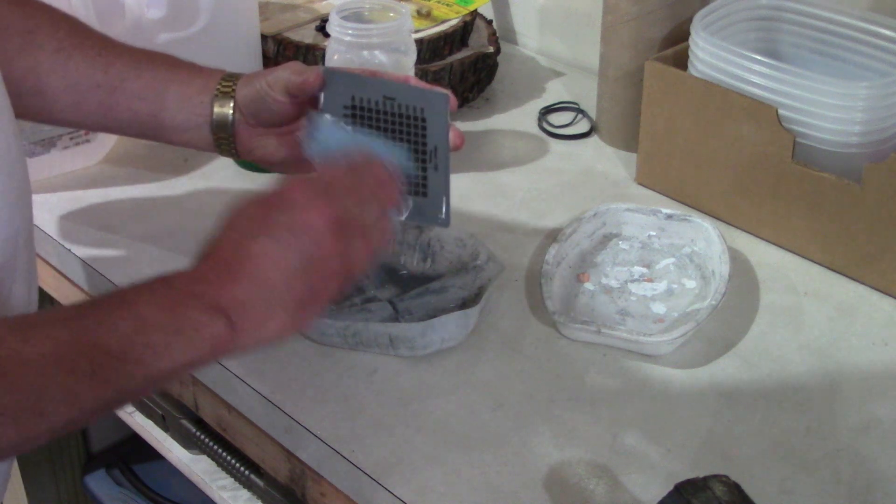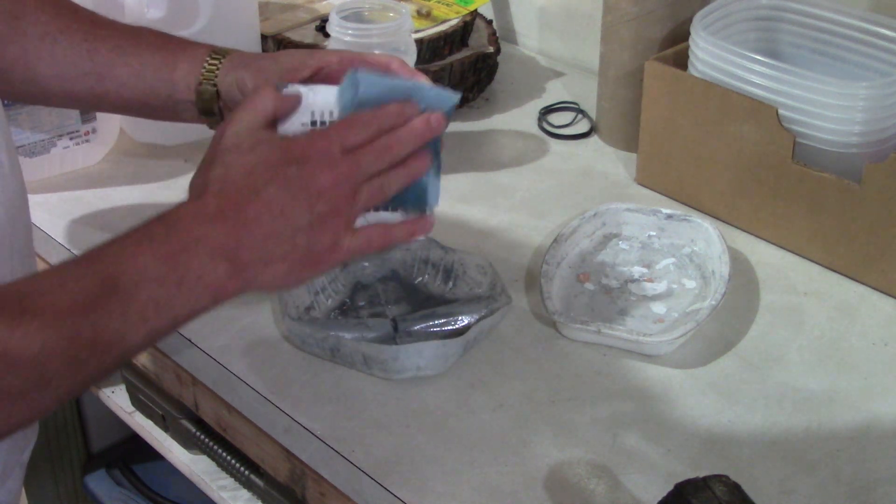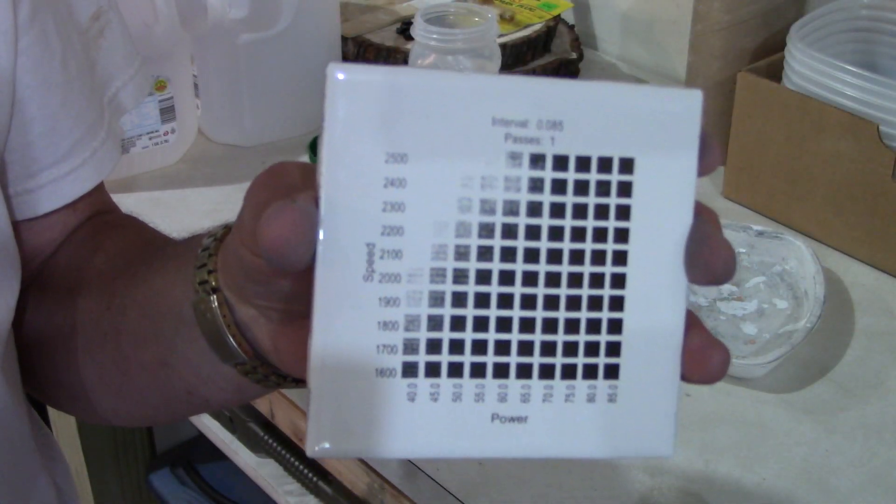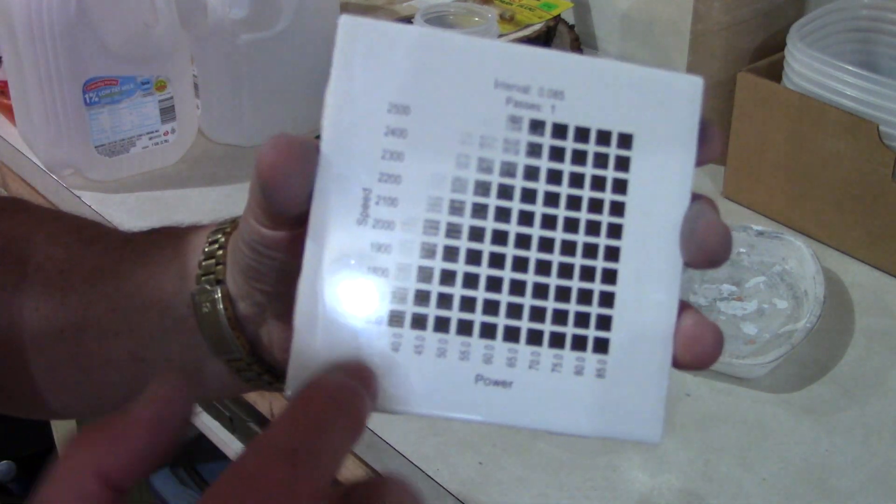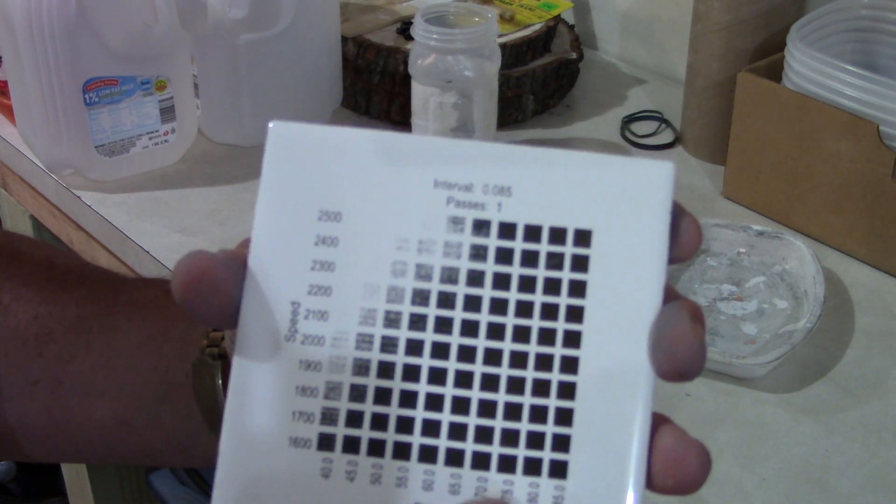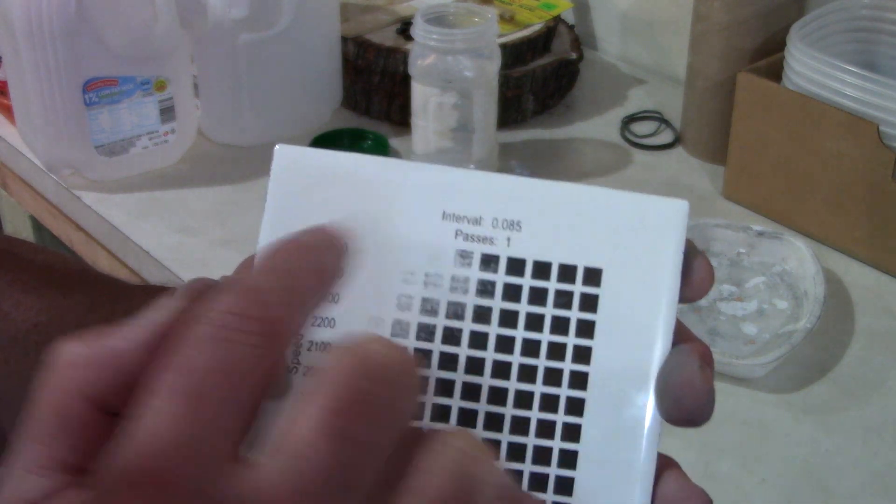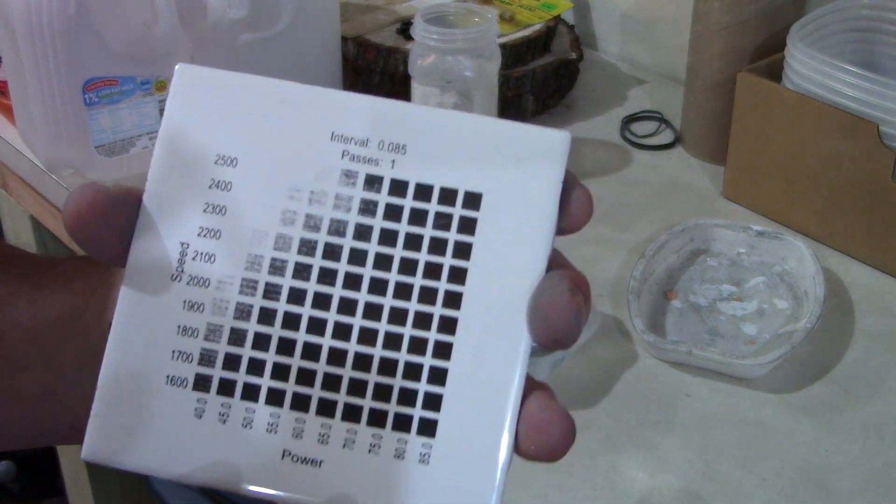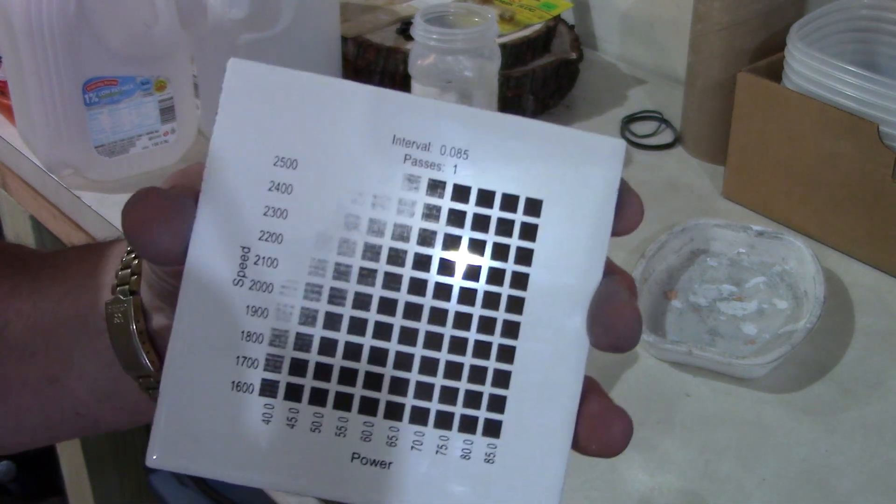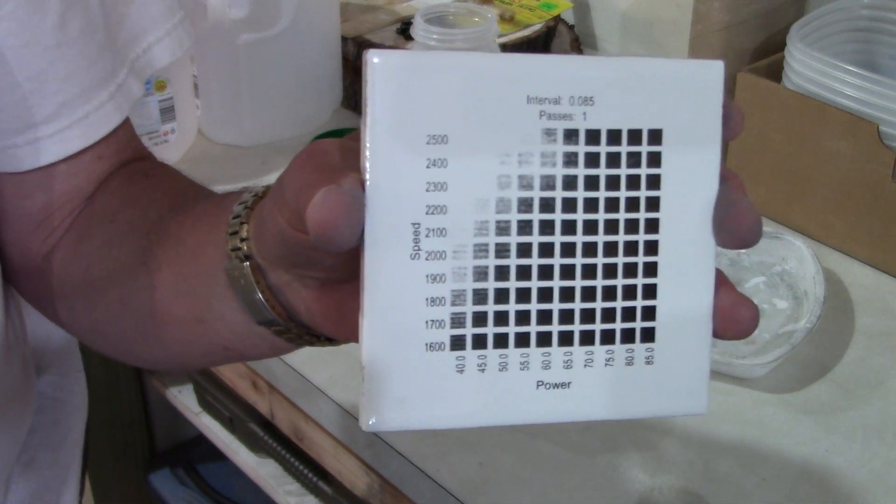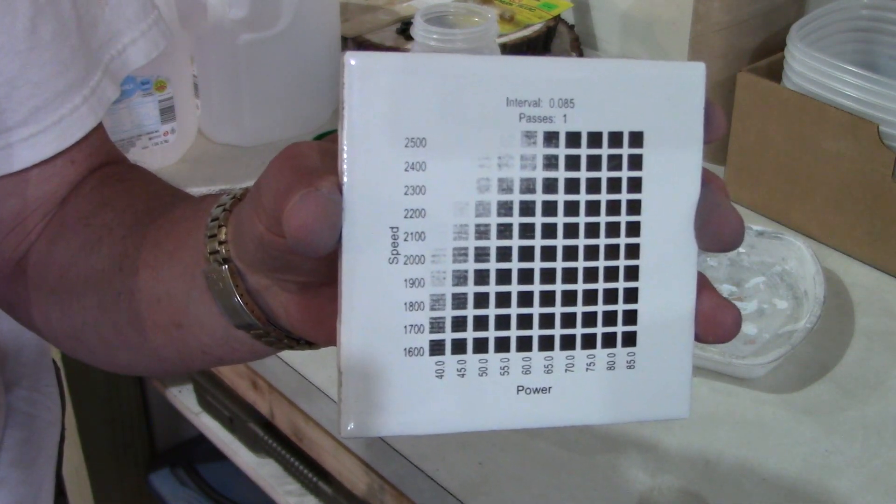So now that it's soaked in a little bit, so it just wipes right off. Here we have the cold galvanizing compound. It turns out really nice. We have all of this area that turned out really nice and black. So at the higher powers, even at 75 percent power, it's pretty much black all the way up to 2500 millimeters per minute. Which means we can burn this incredibly fast. If we even go to a higher power, we get a nice black thing. So these will go much faster than trying to do the white tile method.